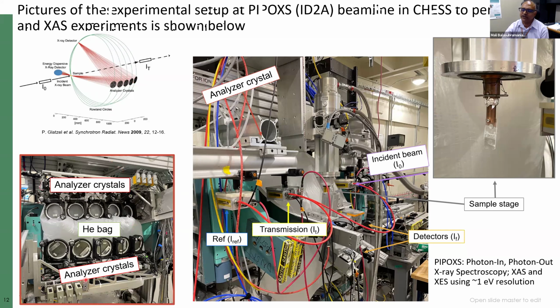They have a setup where you can do two color emissions. So you could potentially look at iron as well as manganese simultaneously in this non-dispersive setup, approximately, I would say, like 0.7 to 1 meter sort of SBCAs. You can get of the order of 1 eV resolution with it. Beautiful setup. The setup is extremely stable. It's a rock. Wonderful work can be done there.